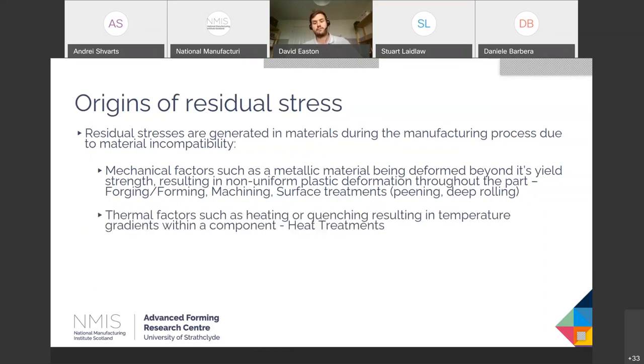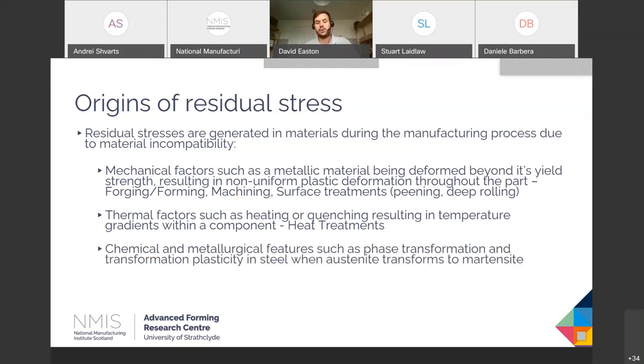We have thermal factors, heating, cooling. So if we take, for example, a part being quenched as part of heat treatment, we're going to get heating and cooling at different rates in the part. This is going to cause temperature gradients. Different regions of the material are going to want to expand or contract differently, and this will result in residual stress. Similarly, chemical and metallurgical features, things like phase transformation, or things like transformation plasticity, can give rise to residual stresses. When austenite transforms to martensite, the volume is different and this is going to introduce stress.